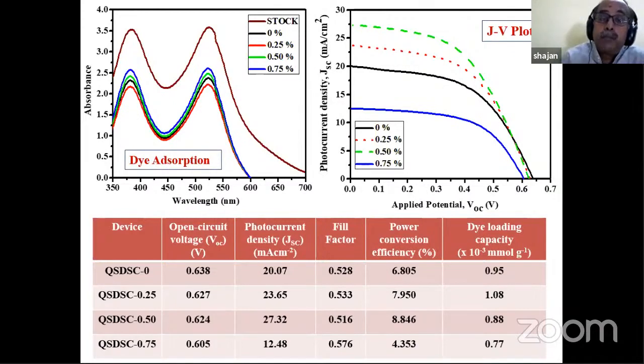And you can see the JV plot here. You can see here the power conversion efficiency of the solar cell that we have fabricated is around 8.8%. This is a significant increase in the power conversion efficiency using solid electrolyte, because solid electrolyte has been reported at around 10 to 11% by using different methods. In our case, we have reached up to 8.8% in the system.